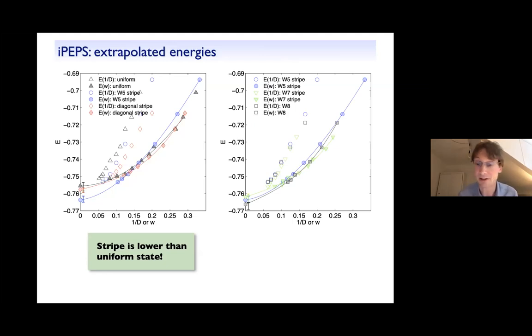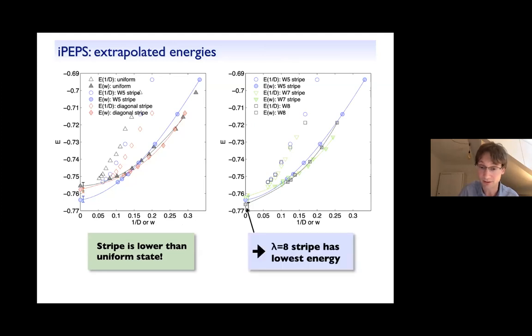So which stripe period gives the lowest energy? Now this is more tricky to do. All the extrapolations give energies which are close together, at least between period 5 and period 8. There's a slight tendency for period 8 stripes being the lowest in energy, but they're really pretty close.